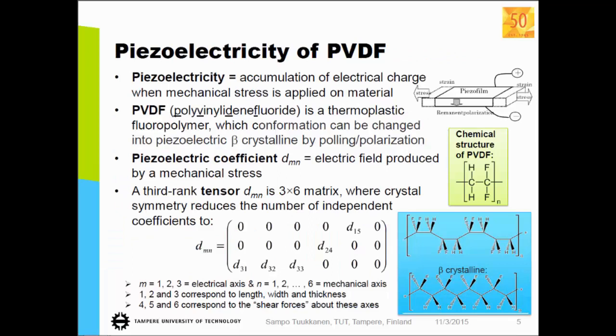So what we have started with is PVDF, which is polyvinylidene fluoride, and here's the molecular structure. So basically, you can change PVDF to the beta crystalline form, which is the piezoelectric form, and then you basically flip the fluorine up and hydrogen down, so you have a molecular level charge, like a dipole moment.